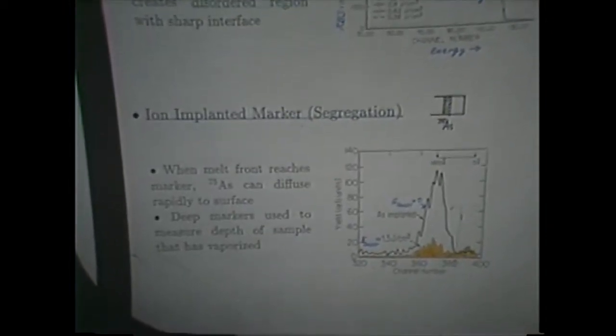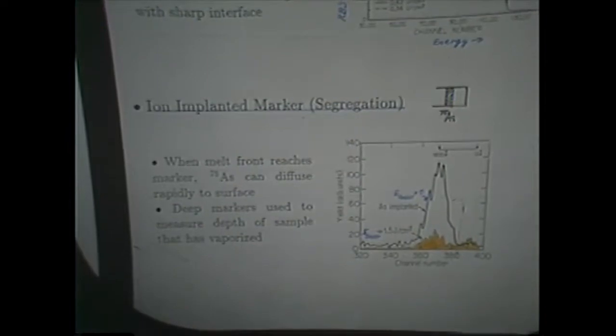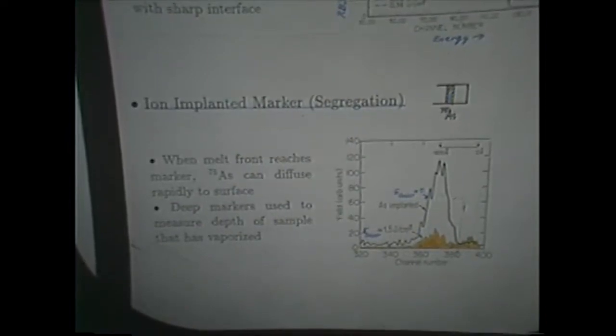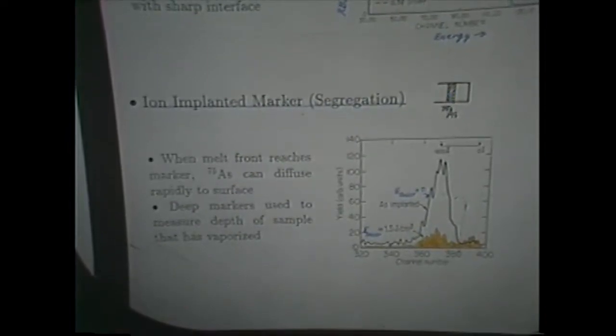So we tried the next experiment, which is a marker. Now, here's a marker of arsenic. We're still going to do Rutherford backscattering. But now we'll do backscattering from the arsenic atoms. Arsenic, being heavier than carbon, will deliver backscattered helium atoms at a much higher energy. So that's separated from the energy that we get from the scattering of the carbon atoms.